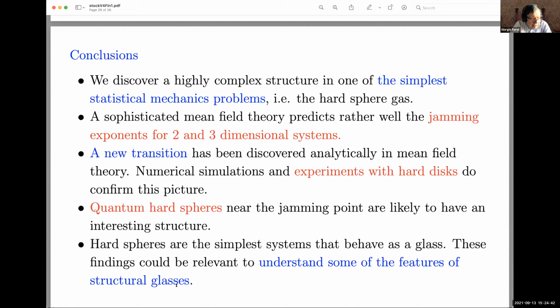If you look at the Ising model, which is the best understood model for statistical mechanics, we are speaking about exponents. Of course, there are two kinds of computations that you can do. One computation is to compute the position of the transition, and of course, the position of the transition in the real world is different for ferromagnets from mean field theory. The thing that you're interested in is universal quantities like critical exponents. These are given by mean field theory exponents in greater than 4 dimensions, and in 4 minus epsilon dimension, they are given by the Wilson expansion, which is correct for small epsilon, and more or less gives a less than 1% value. You can compute to 8th order, 7th order. So what happens in 3 dimensions?